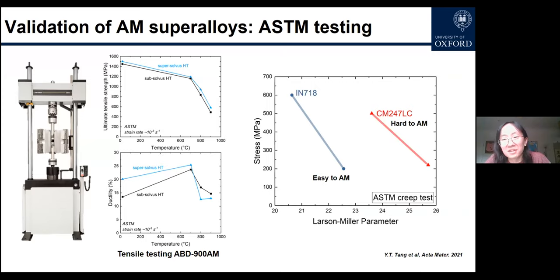There are two benchmarks in here. One is Inconel 718, which is additively friendly. You can make Inconel 718 without too many problems, but it is not designed for very high temperature applications. It is very strong, but not very heat resistant. Compared to CM247, which is very strong at high temperatures, but is just a bit hard to additively manufacture. And as I showed, there are a lot of very critical defects that are present in these alloys.